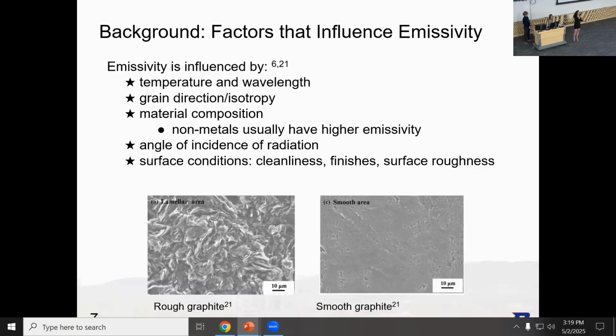And then additionally, your angle of incidence, that the electromagnetic waves are going to emit from your material, depending on the direction of the detector that you use, will influence your emissivity measurement. And then lastly, surface finishes, conditions, cleanliness is huge on emissivity. So on the left here, we have a very rough surface of graphite, maybe an oxidized sample. This will have a higher emissivity because there are more cavities for incident electromagnetic radiation to absorb into the material.